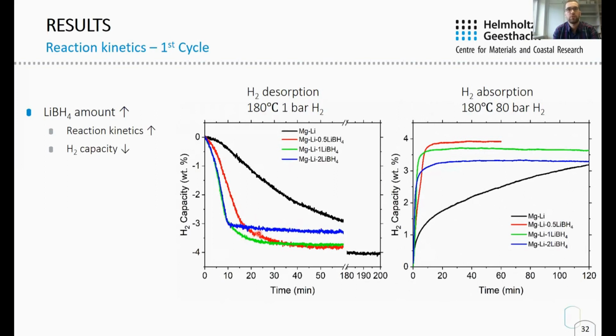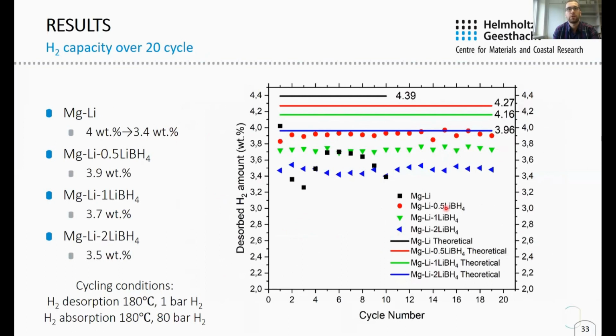Durability of the additive over repeated cycles is also crucial to investigate because the reaction kinetics and hydrogen capacity at the first cycle and then at longer cycle numbers can be very different. Therefore, I did 20 hydrogen absorption desorption cycles for each sample at isothermal conditions. Theoretical hydrogen capacities can be seen in this figure as solid lines. Pristine sample has a theoretical hydrogen storage capacity of 4.39%.